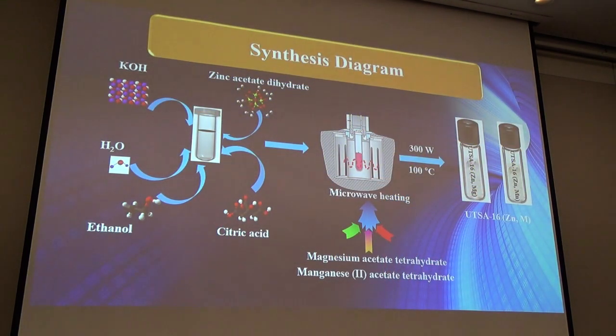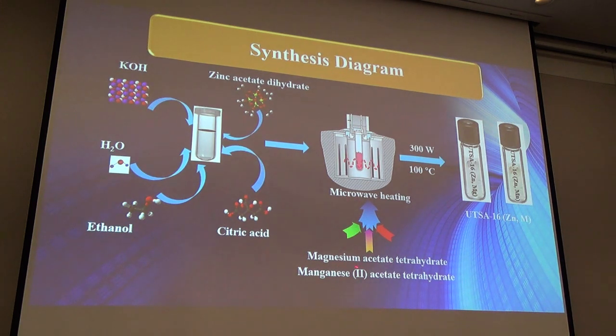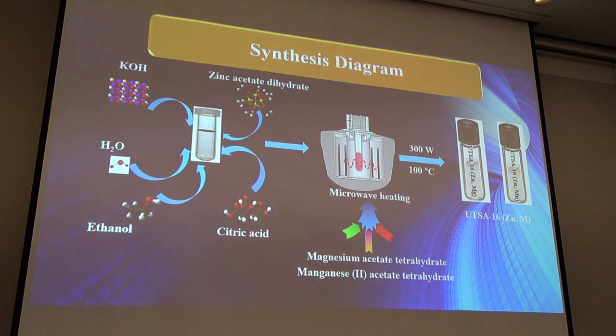Synthesis diagram. For the synthesis of bimetallic MOFs, we use the microwave irradiation method. Here, zinc acetate dihydrate as a metal ion source, citric acid as an organic linker, and KOH were dissolved in a 1:1 solution of water and ethanol. To this solution, magnesium acetate tetrahydrate and manganese acetate tetrahydrate were dissolved, and this solution was heated in a microwave oven at 100 degrees and 300 watts for 4 hours.